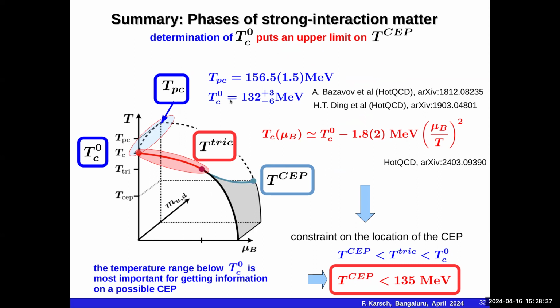So what we learned from lattice calculations is that the pseudo-critical temperature at physical values of the quark masses and vanishing chemical potential drops by about 25 MeV when we go to the chiral limit. And then this chiral limit result for the transition temperature keeps dropping when we switch on baryon and strangeness chemical potentials. And the drop is sort of given by this term here. So it drops by about 2 MeV when the baryon chemical potential over temperature is about 1. Which doesn't sound much to you, but it's in some sense quite substantial.